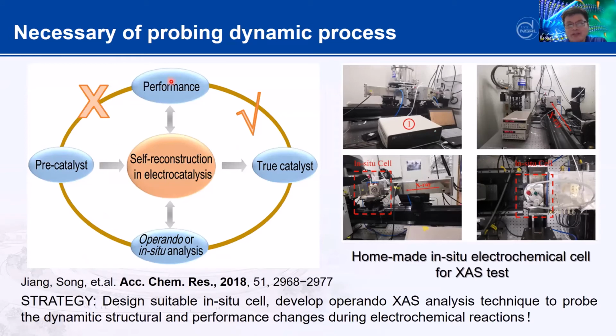You study the performance and you found, okay, this performance looks very good. But meanwhile, the other group say, okay, this performance is not good because the synthesized way may be different, right? So what's the reason? The reason is you try to make the relationship between the pre-catalyst and the performance. But if you really look into the structure, look into the reaction, you will see in many cases the pre-catalyst will self-reconstruct during the electrocatalysis. So that's why you need the operando or in situ analysis.